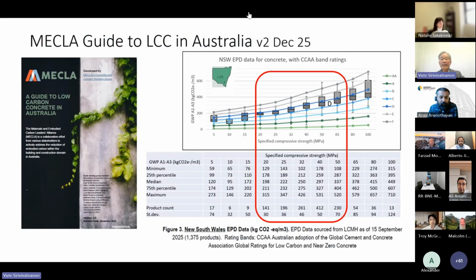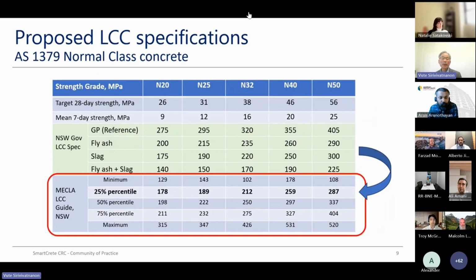Many questions came to us when we introduced all this, on whether the suppliers can actually supply this type of concrete. And we are so happy to see the MECLA low carbon concrete guide, which was released in February this year. It showed that for the range of production by commercial concrete suppliers, most of them are in the range of band D, the lower end, at the 25th percentile. So this is for New South Wales. Here is a comparison between the value we recommend versus the 25th percentile by MECLA. You can see that they agree pretty well, which means that concrete suppliers can commercially supply concrete with that range of embodied carbon.